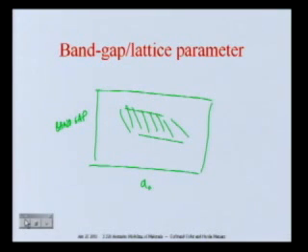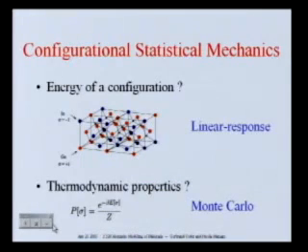But in reality there isn't anything really useful that has, say, the band gap of silicon, but meets the wavelength for which conventional fiber optic cables are transparent. And so there is a lot of effort in trying to engineer alloys or new materials that go towards that sweet spot in which you can grow things epitaxially on silicon, so you can use all your silicon technology, but they have the right direct band gap that is appropriate to optical fibers, 1.5 microns.